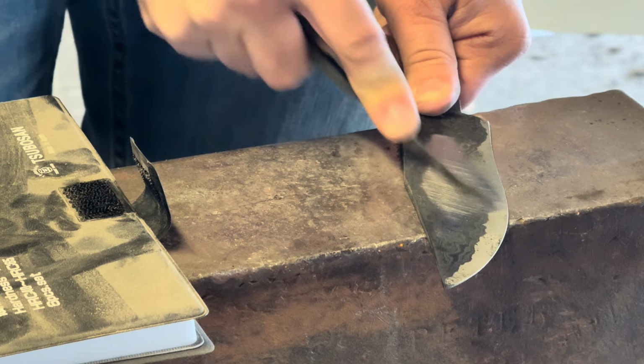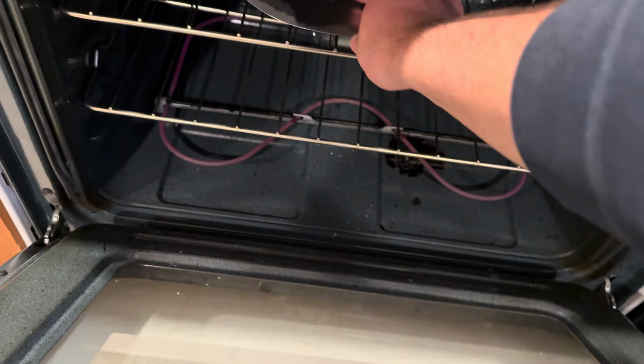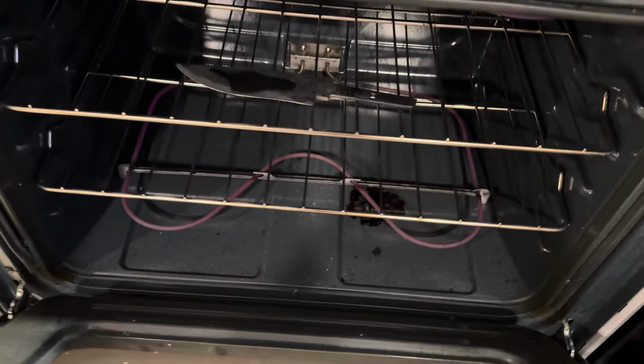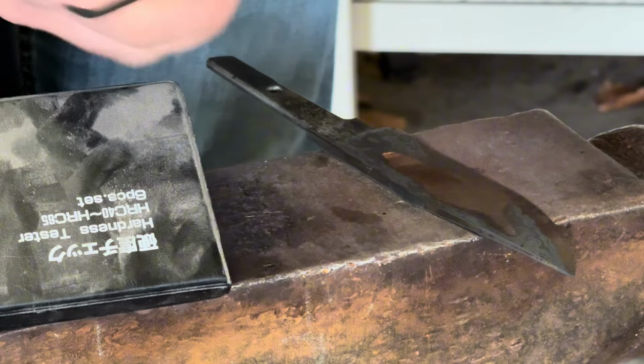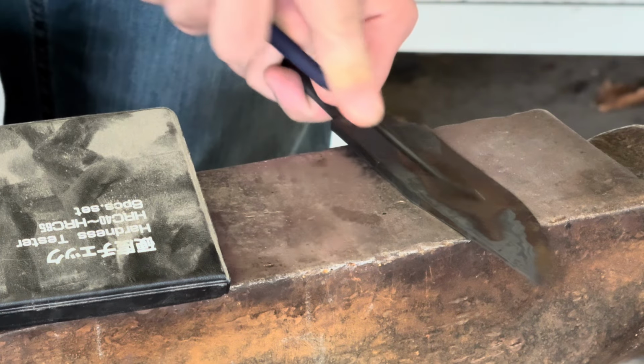The blade is actually too hard now, and it's pretty brittle, so I temper it in my oven to reduce that hardness and add strength to the blade. I plan to temper it down to about 61 or 62 Rockwell. This is the perfect medium of edge retention and blade toughness.